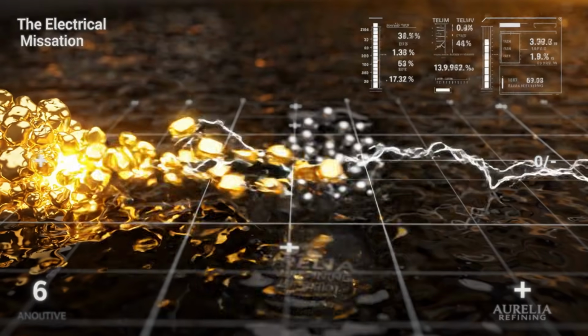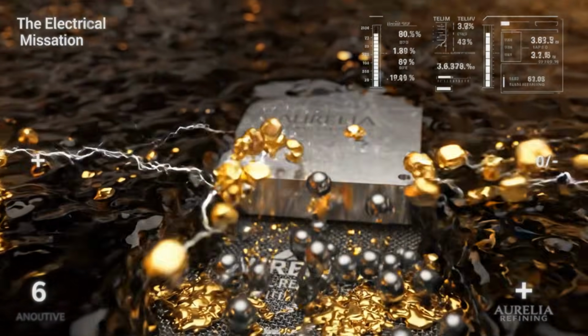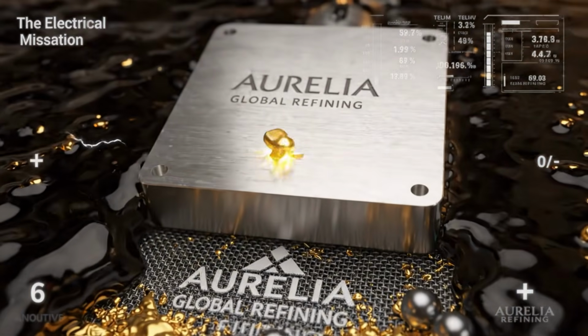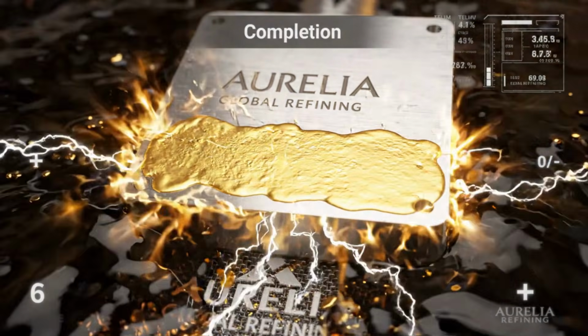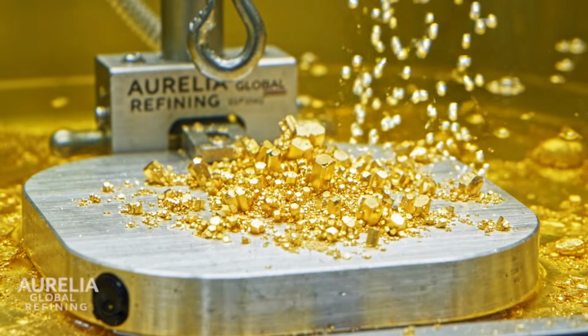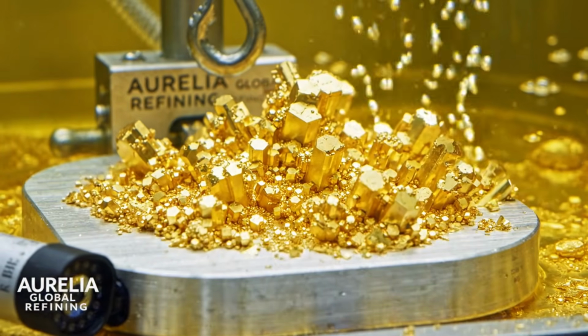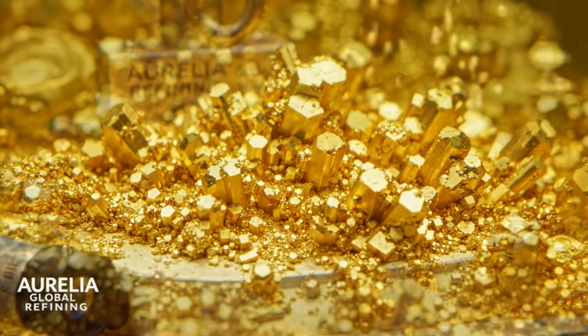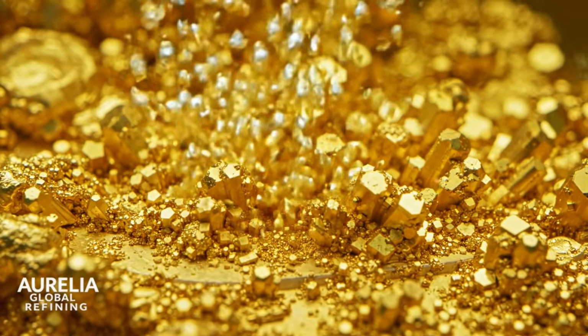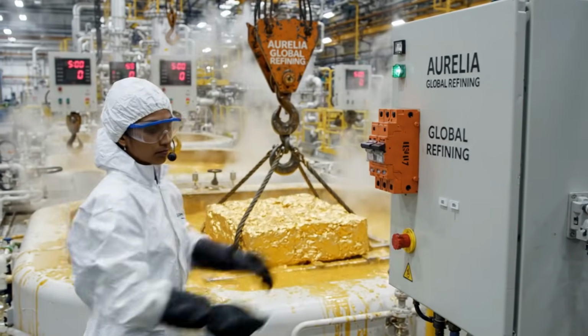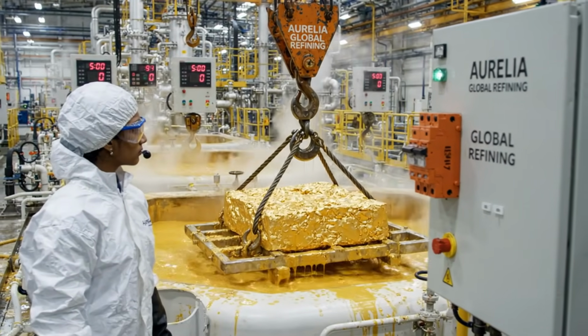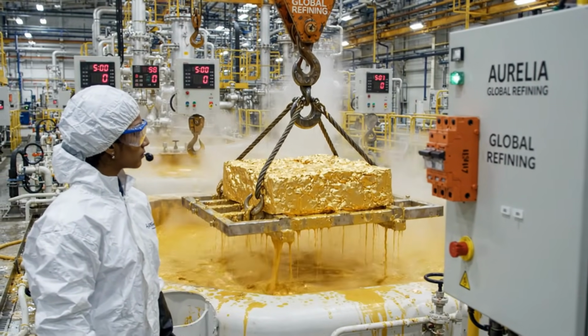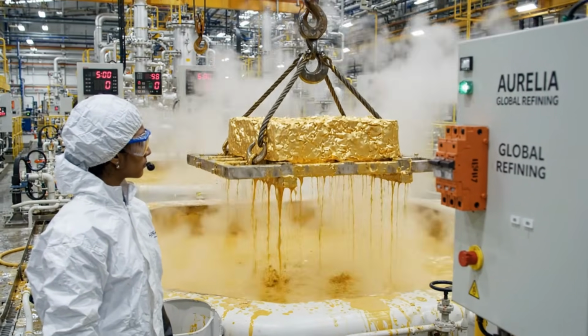The electric charge forces the dissolved metal to travel across the liquid toward the cathode. Pure gold atoms attach themselves to a titanium strip, leaving all remaining microscopic impurities behind. Over several days, the pure metal builds up into a thick, heavily textured golden sponge.